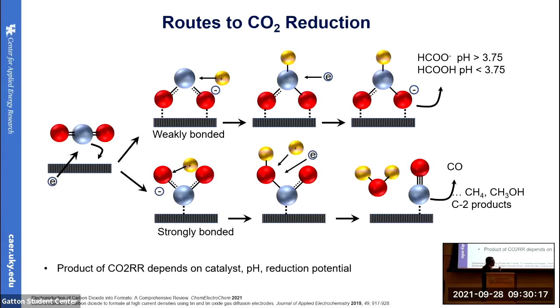If a CO2 molecule is weakly bonded to the substrate, then with protonation and interaction with the electrons, there is possibility of getting formic acid or formate ion if the pH is more than 3.75. If it is strongly bonded to the substrate, there is possibility of getting carbon monoxide, from which other C1 and C2 products can be obtained. However, the actual performance of the catalyst depends on the catalyst itself, pH, and also on the reduction potential.